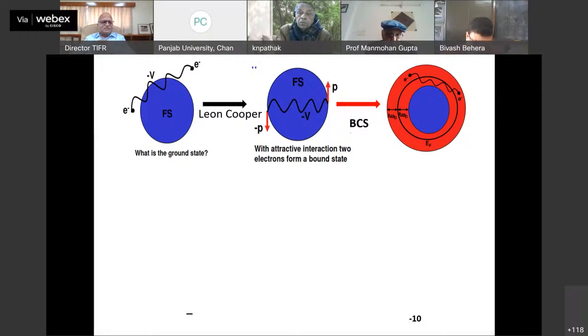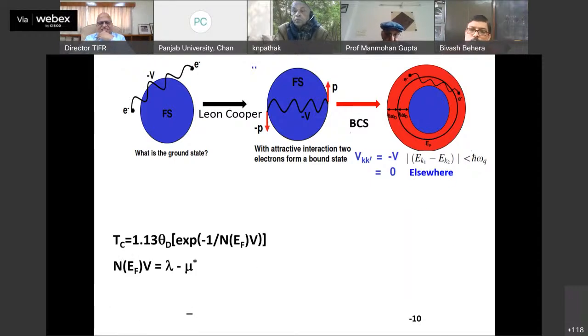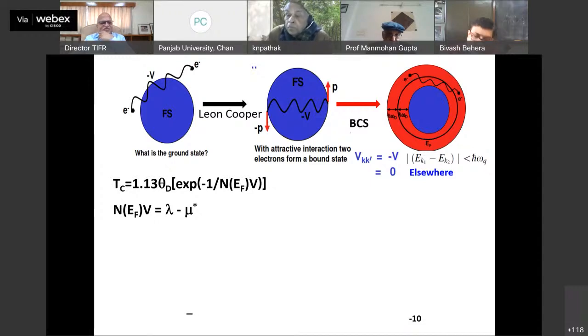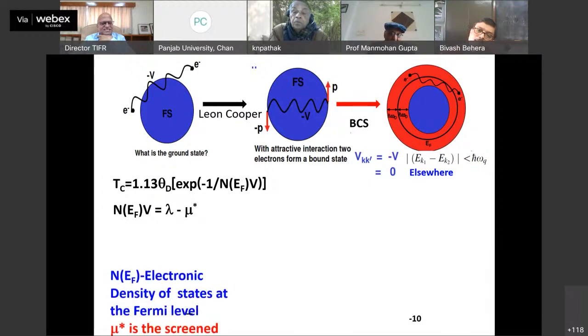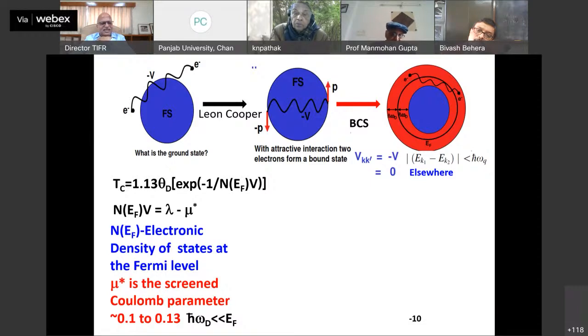They developed a complete theory for these 10 to the power of 22 electrons, which you mentioned. What I've shown here is again an exaggerated view of a shell around this Fermi surface where you have an attractive interaction, and there is no interaction outside this Fermi surface. Using this, the theory predicted a transition temperature of a superconductor in terms of some known parameters. Theta D is the Debye temperature, N(EF) is the density of states, which is related to the electron-phonon parameter lambda, and something known as the screened Coulomb parameter. You know that electrons have like charges and they repel each other, but in a collection of 10 to the power of 22 electrons, there is a screening, and that is what is known as the screened Coulomb parameter.